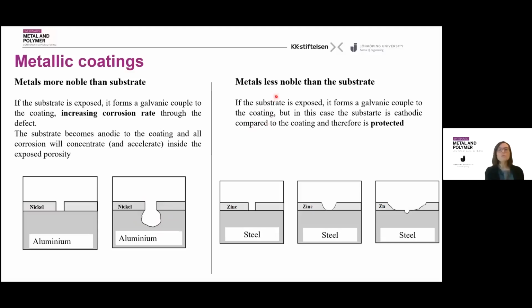It's different if you're able to choose a less noble metal to give protection, because in that case, the galvanic couple would accelerate the corrosion only of the coating, providing extra active protection to the substrate underneath. That can be exploited mainly for steels, not so much for aluminum, unfortunately.